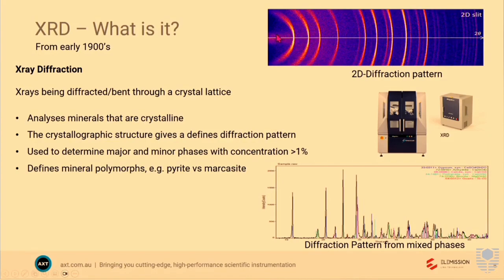So over time, then you've got 1D X-ray instruments which will pick up a one-dimensional line of this X-ray diffraction pattern, and nowadays you've got 2D, two-dimensional detectors. In a perfect world, the XRD pattern is a perfect ring. But if you have large particle sizes or a preferred orientation, you end up with hotspots, so you don't end up with a perfect ring. Or if you want to record a reaction that's changing over time, with a two-dimensional detector, it starts off with one mineral phase and the crystalline diffraction pattern then changes.